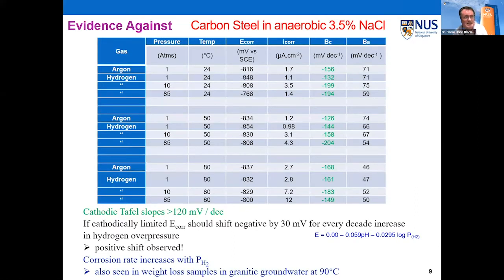This is some data I did years and years ago under waste disposal. In waste disposal, we were always worried about corrosion rates in anaerobic conditions, nuclear waste disposal. You're going to bury that waste for 1 million years, so even low corrosion rates are quite important. What we have here is increasing hydrogen pressure, more and more hydrogen pressure. Again, we typically see about 120 millivolts per decade Tafel slopes for the cathodic reactions.